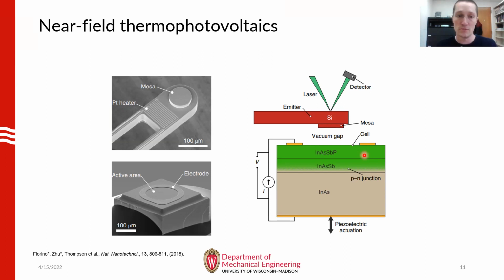Okay, so in this experiment, I fabricated the emitter device that you see in this electron micrograph here. This is essentially a cantilevered structure that we can heat up by several hundred degrees to simulate a source of waste heat. Okay. The PV cell in this experiment is shown in the electron micrograph below. This is a commercial device. And so under high vacuum conditions, we were able to precisely parallelize the surfaces of the emitter and the PV cell in the orientation that you see here.